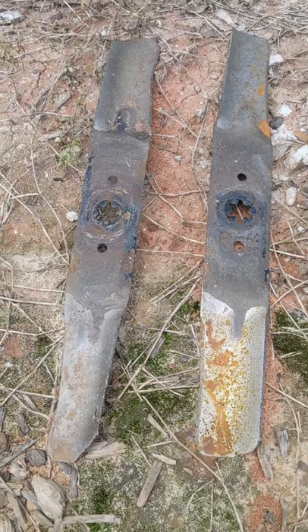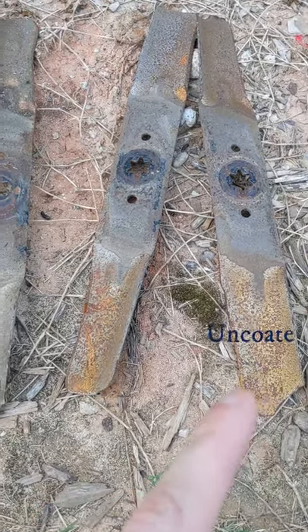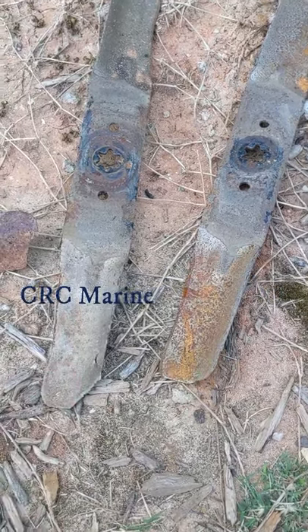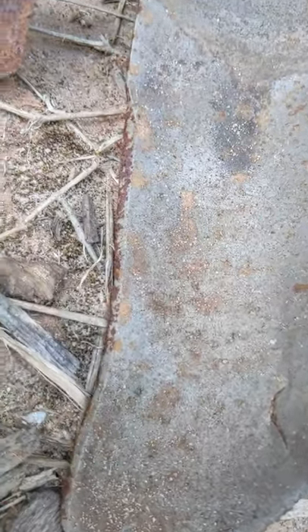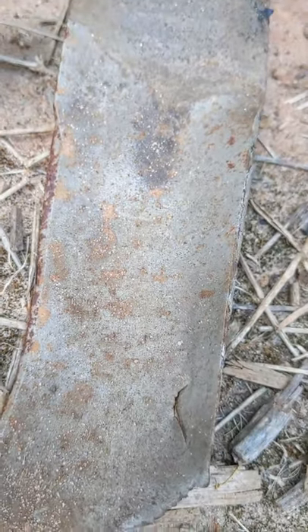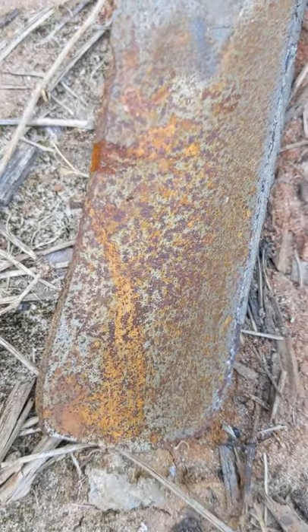It has been since June 25th that I coated these. That is uncoated, that is Fluid Film, and that is CRC. The CRC does show some signs of rusting — you can see on the blade edge where I did not get a good coat, it's quite rusted. Both sides of the blade have a little bit of rust.